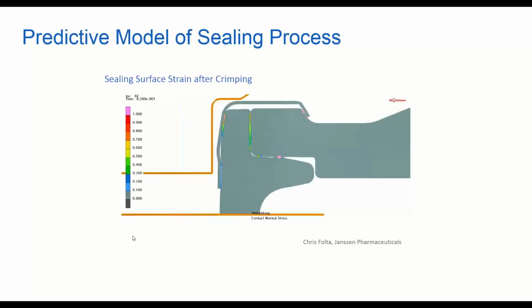Good. So obviously the stopper is inserted, but the colors, the pink being the greatest, is that surface stress, and that's where the greatest part of your seal is occurring. And what we want to do is maintain that throughout the process. And as Derek had pointed out, when you go below the glass transition temperature, the rubber becomes somewhat rigid. It also begins to contract. And if we could continue this animation showing that, you would see that contraction, but you would also see those forces decrease, and the ability to maintain a seal would be compromised. However, what we have shown is that the tighter the seal to begin with, the more likely it will maintain sealing or integrity even in the deep cold storage temperatures.